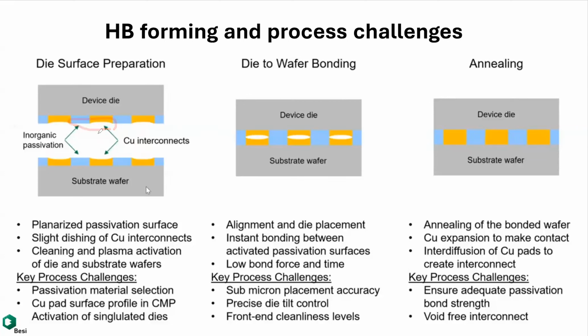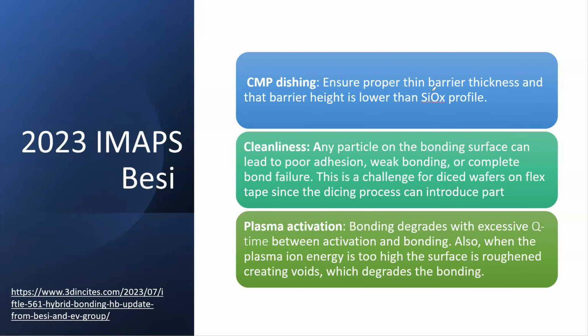They need to make sure copper is lower. And to make that happen, you have to rely on CMP. So CMP plays a key role in ensuring the profile of the copper and the dielectric is what you want. Sometimes you will see that in some special cases, which I'm going to mention later, they actually want the top copper to be higher than the outside. So we will see what's happening in the later foils. But this is what they say, right? This is a POR process. The copper layer has to be lower than the SiO2.